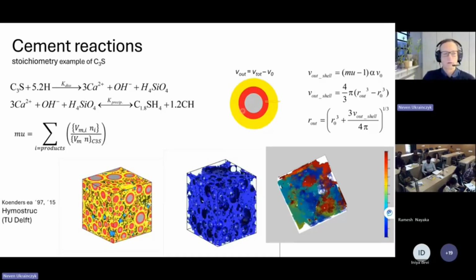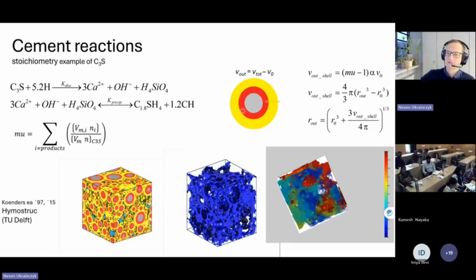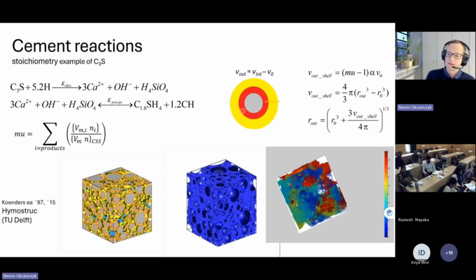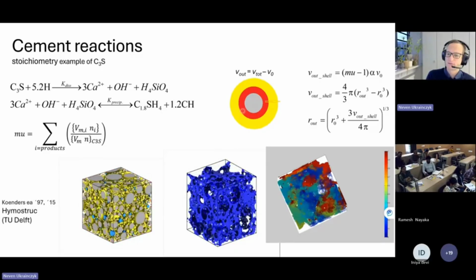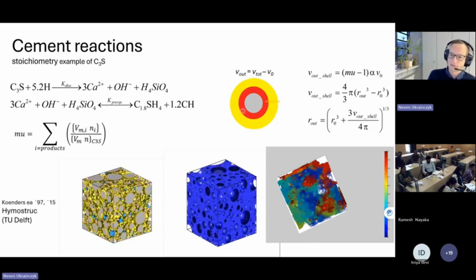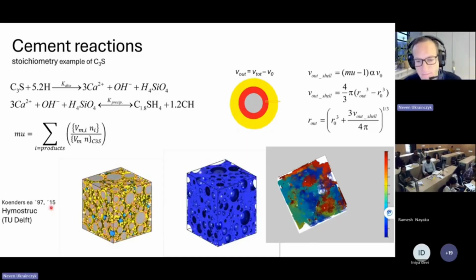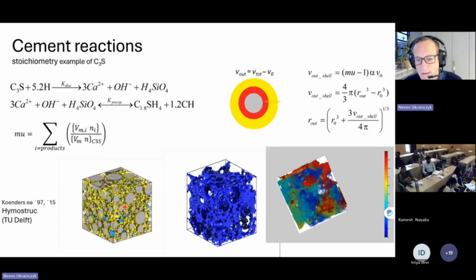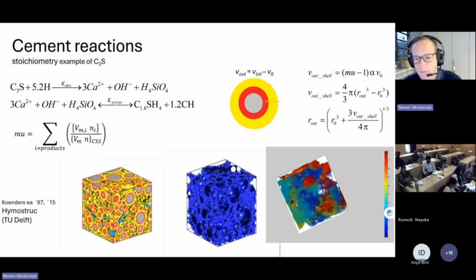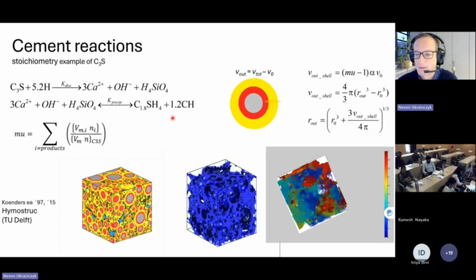And then you have more overlap, so you again need to increase, but luckily this is converging. And then finally you can calculate the volume, so that the sum of the total volume is respected, that you don't lose any volume or create additional volume because of this overlap. There is an overlap algorithm made also by Eddy and by Van Breugel in a statistical approach, and actually it converges, so it is possible to do this overlap algorithm.